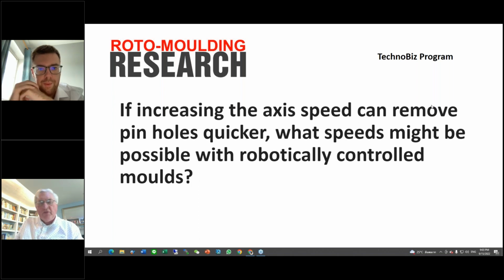Yeah, but as we were discussing earlier, I think as you increase the rotation speed, you're picking up less powder onto the surface on each rotation. So you're giving it a better chance to melt and start to sinter out before you're adding too much powder. You're not adding too much powder in one go. It's being added a little bit at a time. Whereas with a slower speed, the buildup in powder on each turn is thicker, and you're adding more powder, and therefore entrapping more air. Potentially, I don't know. That's just how I'm thinking about it at the moment.